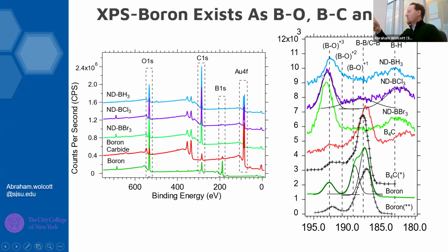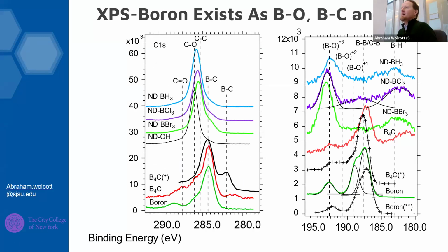So this would be boron-carbon, boron-boron, and boron-oxygen related bonds. And the more that the boron is oxidized, the farther that peak would shift from +1 to +2 to +3, ranging from about 190 eV to about 193. So we're putting that into summary. If we look at the carbon, again, we get this mixture. It's not looking exactly like boron carbide, but it's sort of this agglomeration.